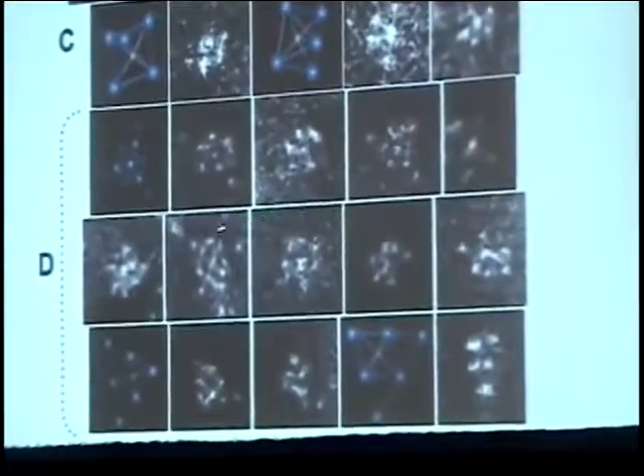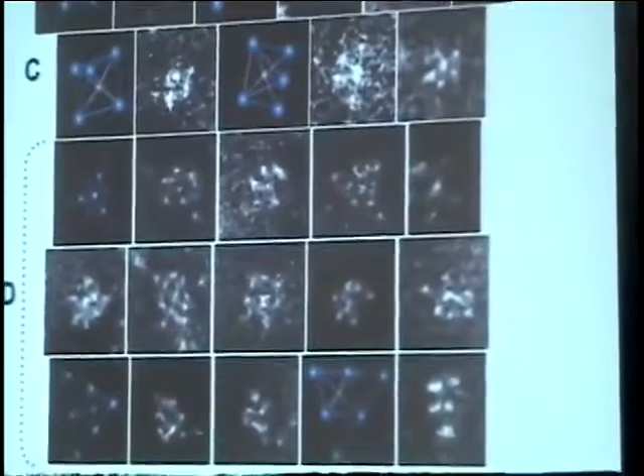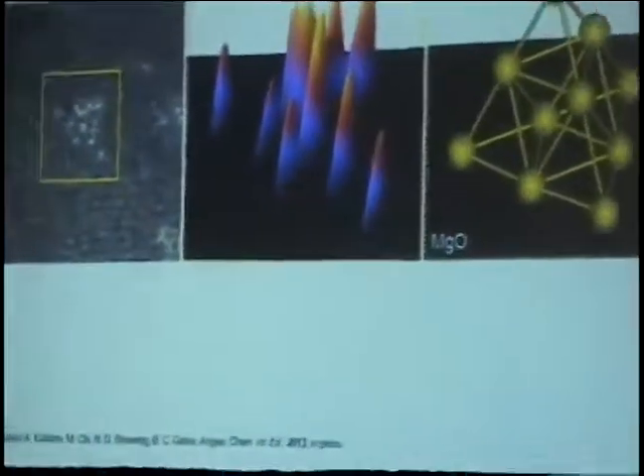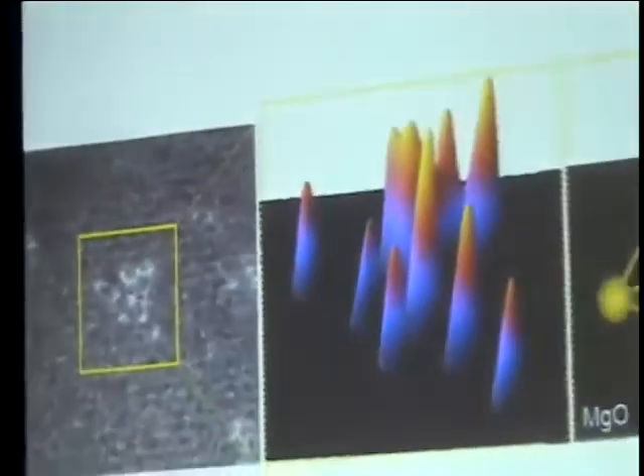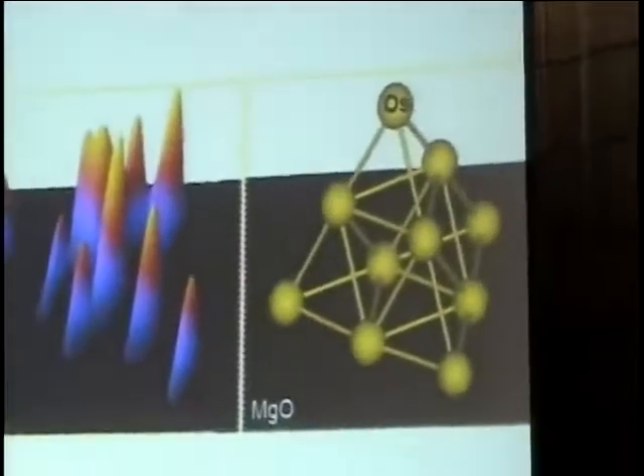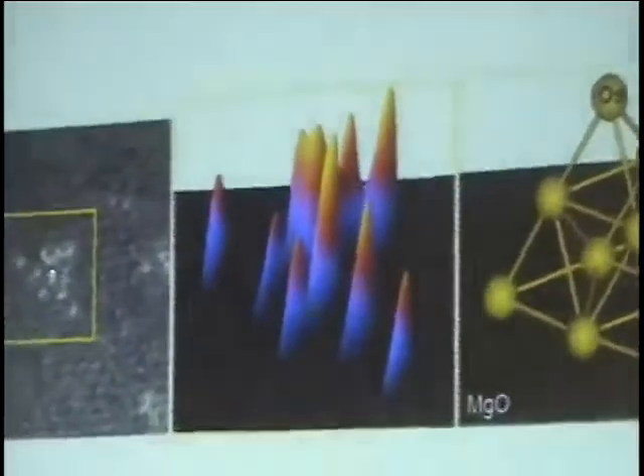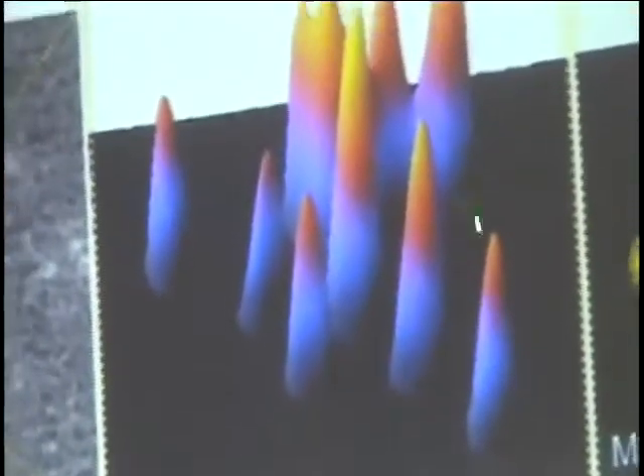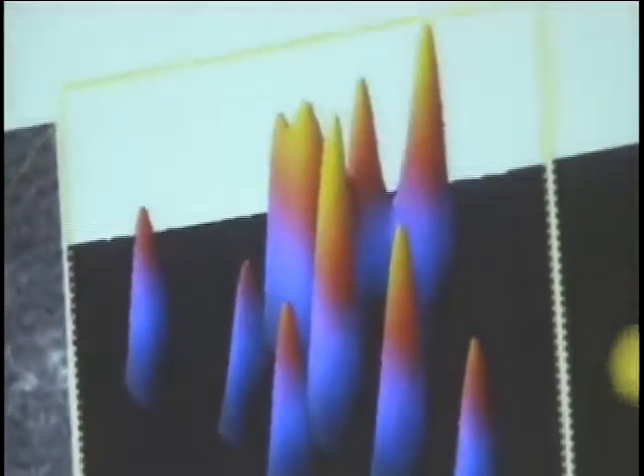And so you might be a little more skeptical of what I'm showing you. That's your privilege. So maybe a little more specific about how we're determining the number of metal atoms in each of these clusters. What we do is an intensity analysis, and I'm not going to give you detail about this, but my students spent months doing this. Take one particular image, like this one, which we call a deca-osmium, do the intensity analysis, and count them: 10 osmiums, indicating that it's really a deca-osmium cluster.